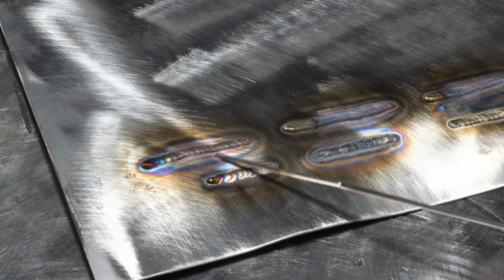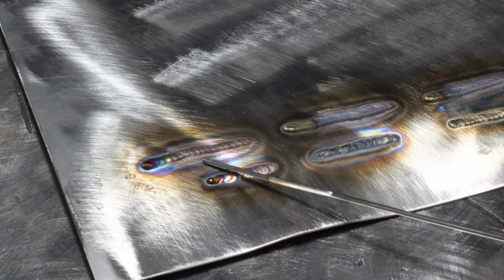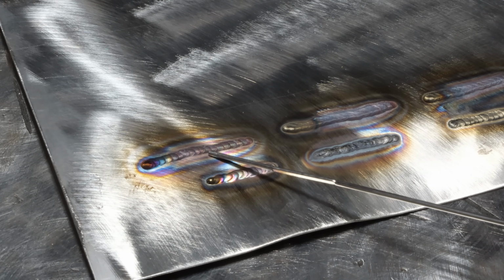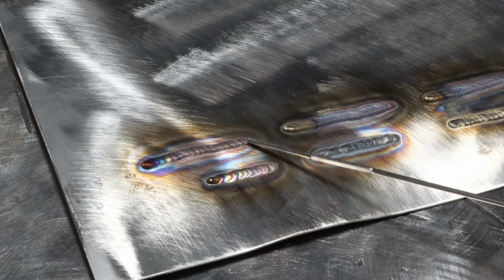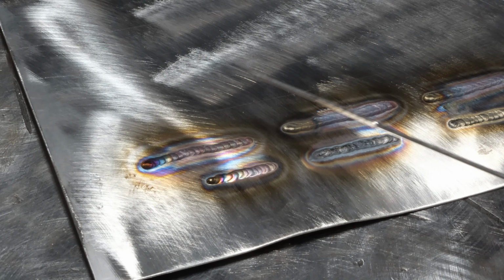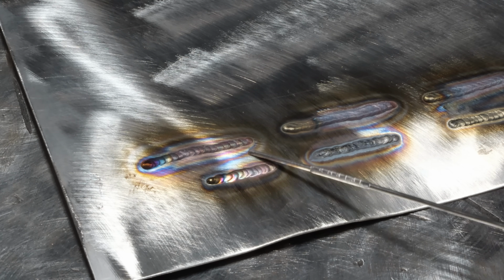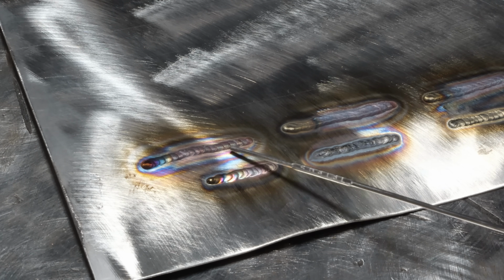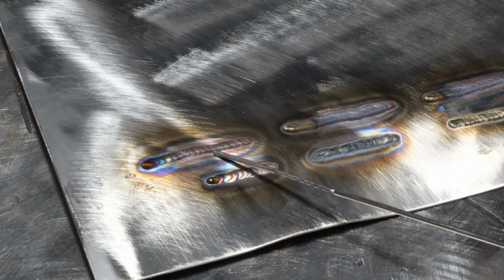This guy right here, I ended up upping the argon flow to 30 cubic feet an hour and settling at 40 amps. And you can see how everything is already starting to look better. The red is not really a defect. It just means that it was fairly hot when it was exposed to oxygen.